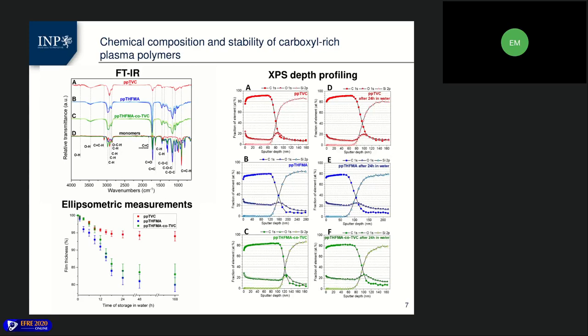After 24 hours of immersion in water, there were no dramatic changes in the chemical composition. However, the overall intensity of signals was slightly lower compared to freshly deposited films. So the decreased signal intensities in FTIR spectra were assigned to the thickness losses of the coating.